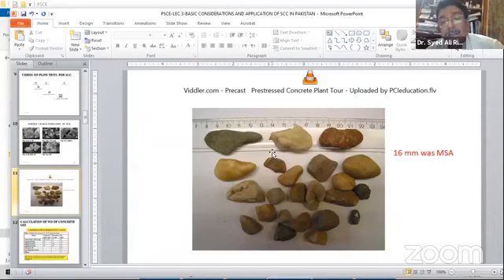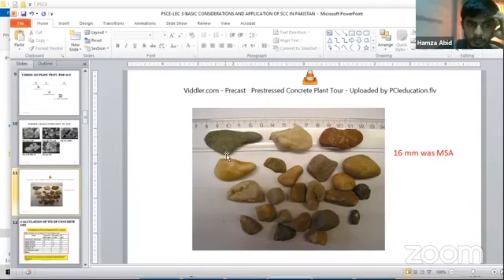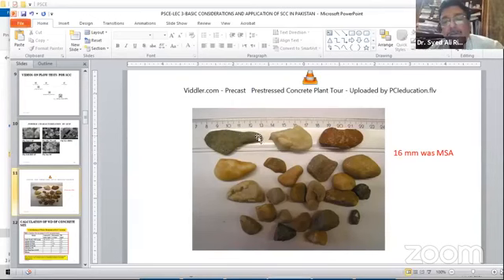And then natural aggregates were used. The maximum size of aggregates was 16 millimeter, but if you can see, some of the aggregates were going straight to 5 centimeters long, but they could have passed from the minimum dimensions. So if you get more of these particles, then the chances of blockage are quite a lot. So you should be careful about the paste content, because in such cases, paste is the vehicle for the transport of the aggregate phase. So you have to examine the shape and size of the coarse aggregate.